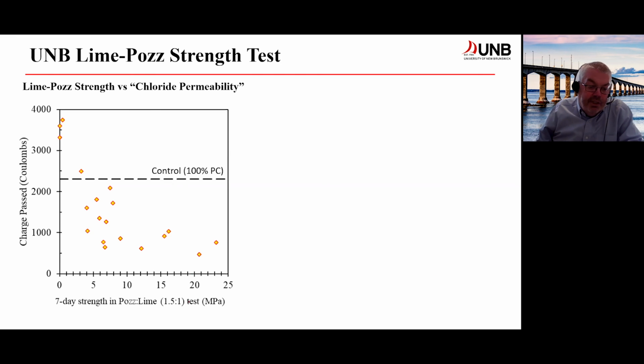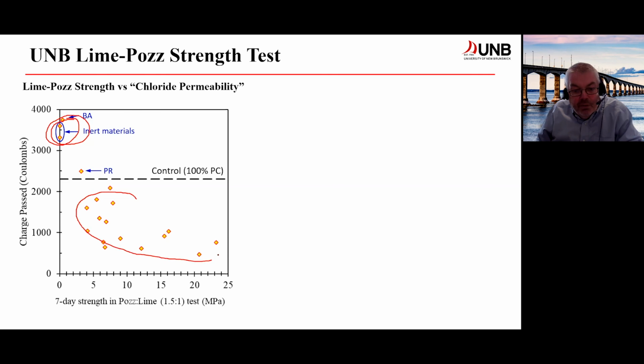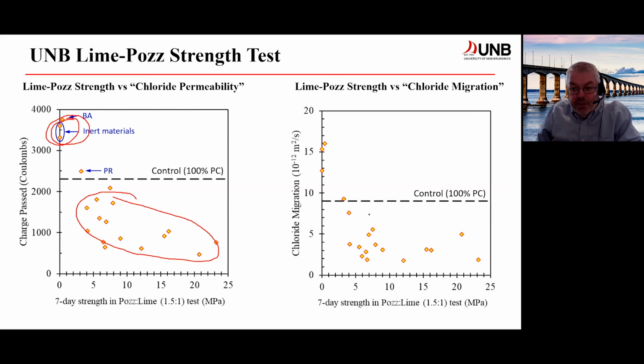So again, a good correlation between the pozzolan lime strength and the charge passed in concrete. This is the rapid chloride permeability test, C1202. And again, inert materials give you no strength in the test. They increase the rapid chloride permeability, whereas materials that perform well in the pozzolan lime test also perform well in concrete in terms of reducing charge passed. And we get the same behavior if we look at chloride migration.